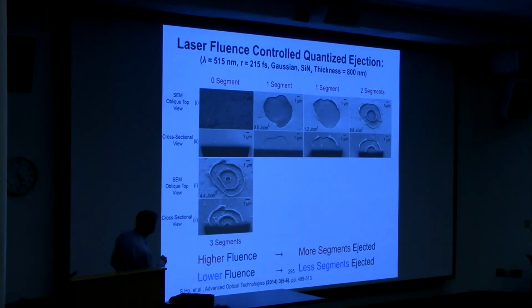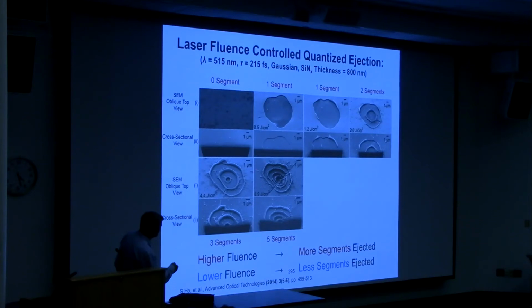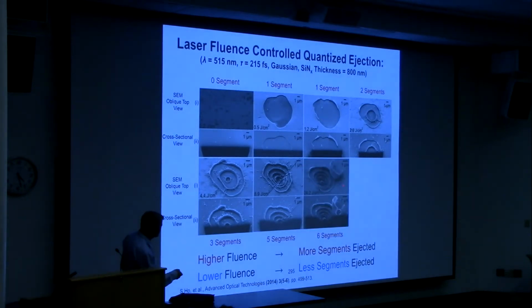So here's a sequence of images where you see at a threshold fluence, one layer ejected. Then you see, with a Gaussian beam, an inner second layer ejected. And this diameter opens up, and you can see layers peeling off. This is good quality film. I thought the student was making crappy film when we first saw this, but it turns out it was this interferometric effect. It's a really neat effect.